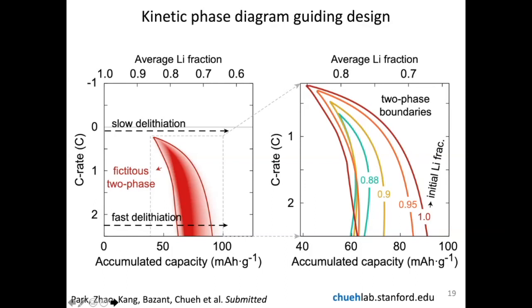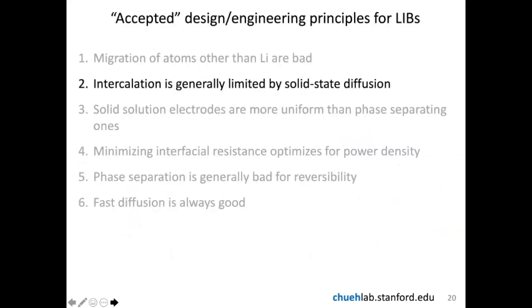In the layered oxide, it's very common not to fully relithiate upon discharging. So this two-phase regime will strongly depend on what lithium content you start with. So these are very interesting insights on the phase diagram for the kinetic behavior of the system. So coming back to the design rule, here I'm showing you that intercalation is not always limited by solid-state diffusion. It can sometimes be limited by the interfacial reaction, and this can have strong implications on how heterogeneity develops within the material.